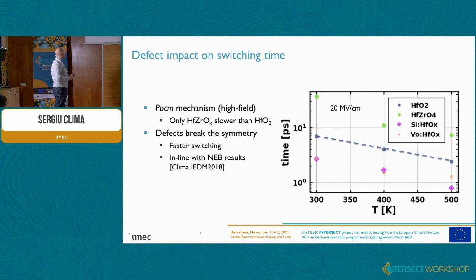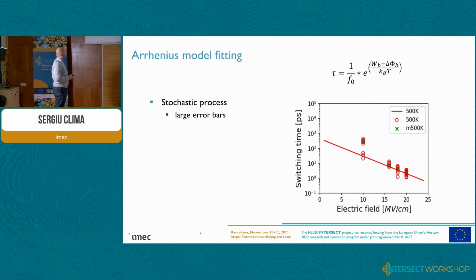And faster switching when we have higher temperature and higher fields. This is intrinsic behavior of the bulk of the material, not considering the grain boundaries and other extrinsic factors, which we did not consider in this work.